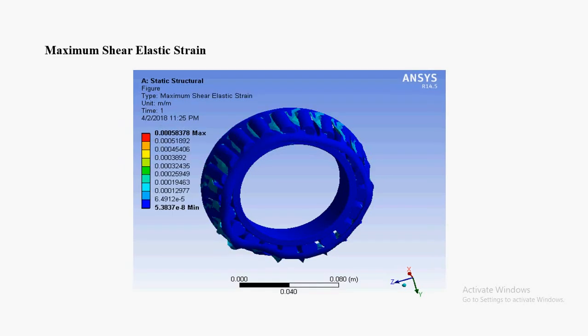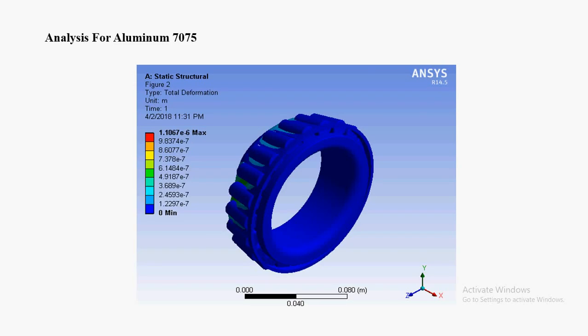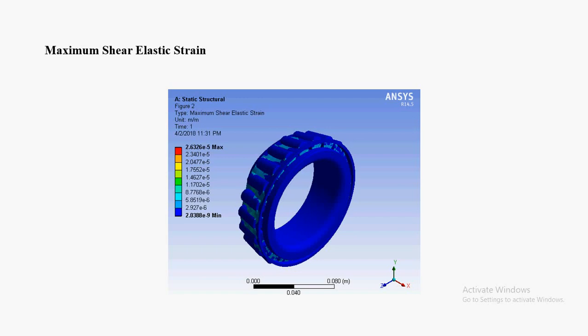And this is the analysis for the steel. This is the total deformation test. In total deformation we can see that at a particular load stainless steel got some deformation, and this is the maximum shear elastic strain for the same load, and we did the same test for the aluminium 7075. For the same load the deformation is slightly less in the aluminium, and also the maximum shear elastic strain is less when compared to the stainless steel, which tells us that stainless steel is not that better when compared to aluminium.